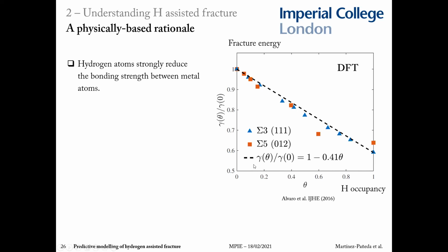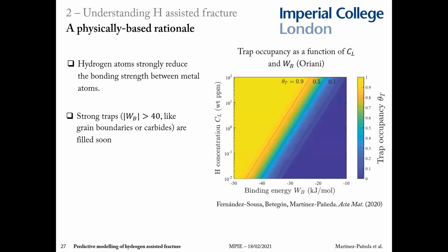And so that is the next research question. So where are we in this hydrogen occupancy axis? How full of hydrogen, for example, are our grain boundaries? And the answer comes from the well-established mass diffusion laws. Specifically from Oriani's equilibrium, you can relate the hydrogen concentration in the crystal lattice, which is the y-axis here, with the occupancy of a trap, this theta T, as a function of the binding energy of the trap. And what we learn here is that the strong traps, such as grain boundaries, with an absolute binding energy that is 40 kilojoules per mole or higher, will be essentially full for hydrogen concentrations as low as 0.3 ppm.